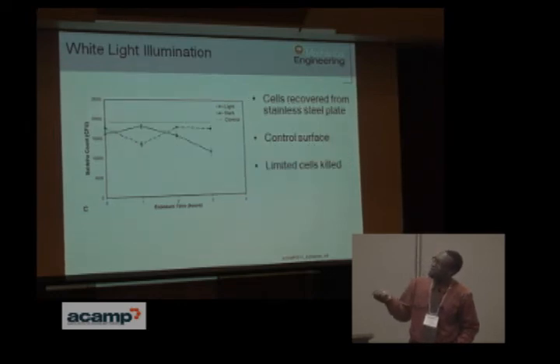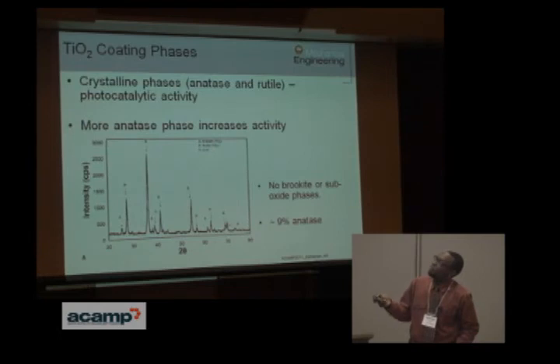And we also did the same thing on stainless steel, just to show that whether or not you shine light on stainless steel, the cells do not get destroyed. You're seeing the effects of the copper and the TiO2 very nicely. Okay. And very quickly, in terms of why TiO2 actually destroys bacteria, it is because we have a material phase known as anatase within the microstructure of our coating. There is no brookite, no suboxide phases, no amorphous phases. We have pretty much rutile and about 9% anatase, which is responsible for the photocatalytic activity that we see.